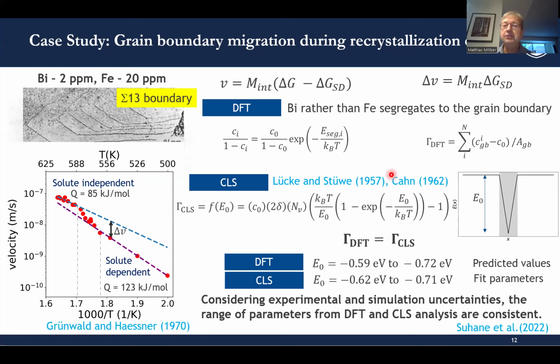And then we can use the classical solute drag model, Cahn, Lücke, Stüwe. They assume a very simple potential well at the interface, a triangular-shaped potential well with a depth of E0, which is the representative binding energy. We can calculate in this solute drag model what the enrichment as a function of the E0 value will be. And then we can say, well, we set these two enrichment factors equal. And out of this, we can estimate from the DFT data what the depth of this potential well in Cahn's solute drag model should be. We get values between 0.6 and 0.7 eV. And if you just do the classical fit of the experimental data to the solute drag model, we get very similar values for E0, also between 0.6 and 0.7 eV.